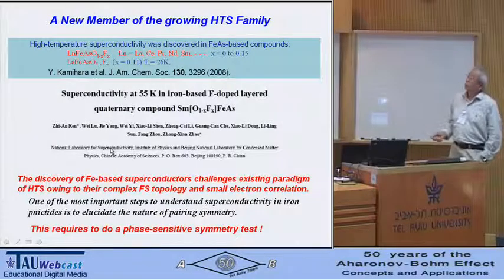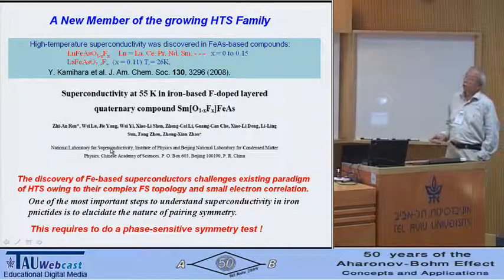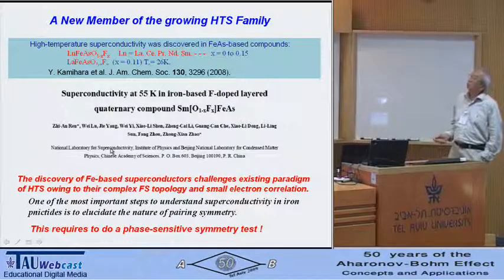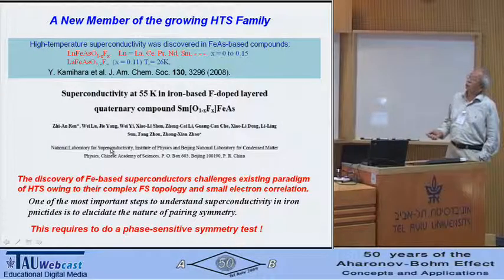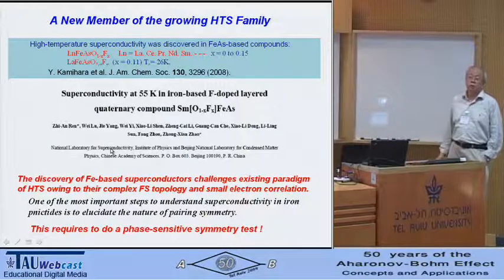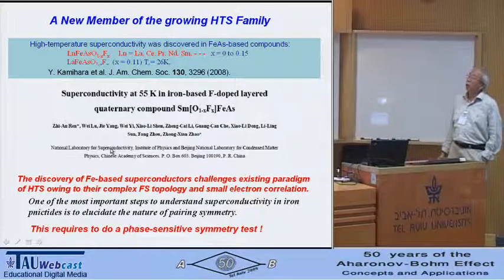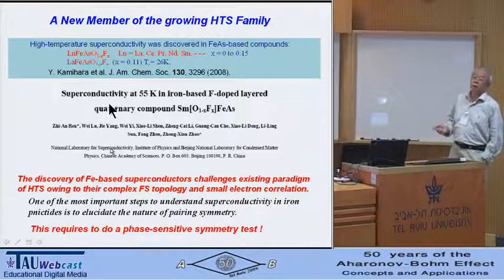And scientists at the Chinese Academy of Sciences, Beijing, China, replaced this rare earth, lanthanum, by other rare earth elements, such as samarium and neodymium. They managed to get the TC up to 55 degrees K.